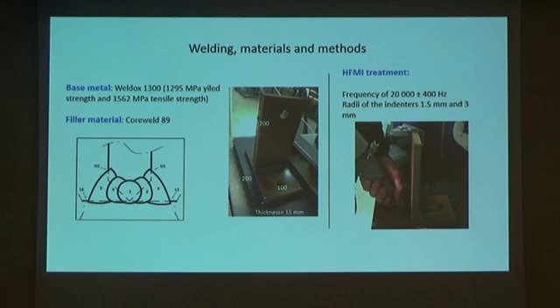High frequency mechanical impact treatment was done in France by Sonats with a frequency of 20 kilohertz. 3 mm radius indenters were used for the upper weld toes U1 and U2, and 1.5 mm radius indenters were used for the lower weld toes L1 and L2.